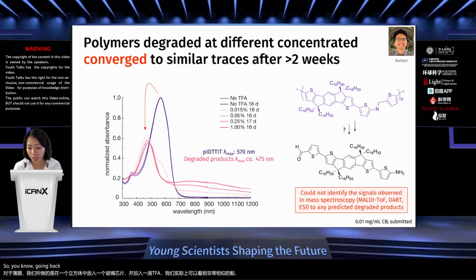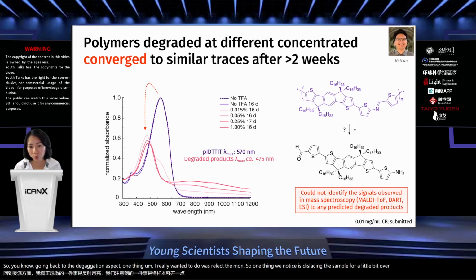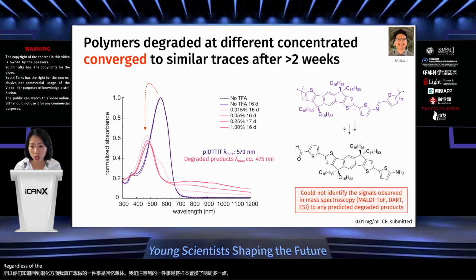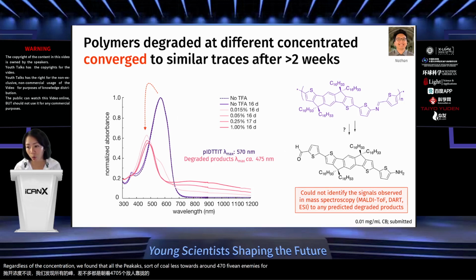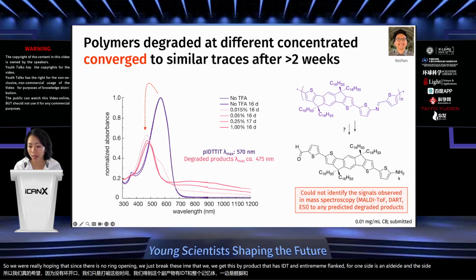So going back to the degradation aspect, one thing I really wanted to do was recollect the monomer. So one thing we noticed is just placing the sample for a little bit over 2 weeks, regardless of the concentration, we found that all the peaks sort of coalesced towards around 475 nanometers for the degraded product. So we were really hoping that since there's no ring opening, we just break this imine bond, that we get this byproduct that has IDT and then thiophene flanked, where one side is an aldehyde and the other side is an amine.